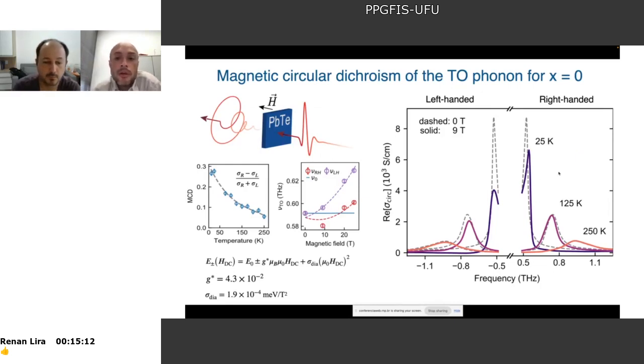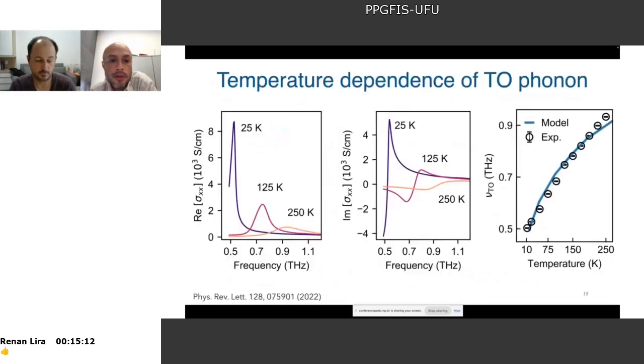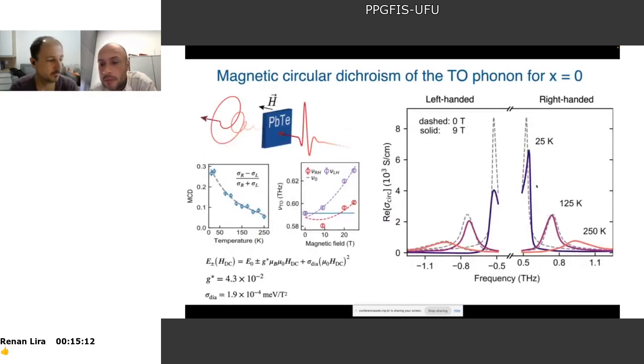We will compare later. So here I show you the same thing, but now I combine the linear components of the measurement in left-handed and right-handed. Here on the left we have dashed lines for 0 Tesla, solid lines are 9 Tesla, at different temperatures. These three curves are the curves that I showed you before. Let's come back here. These three curves here are these three here. But you can see two important differences. First, left and right have different heights at the same temperature. This one has this, and this one is much taller. So there is a very strong difference in height.